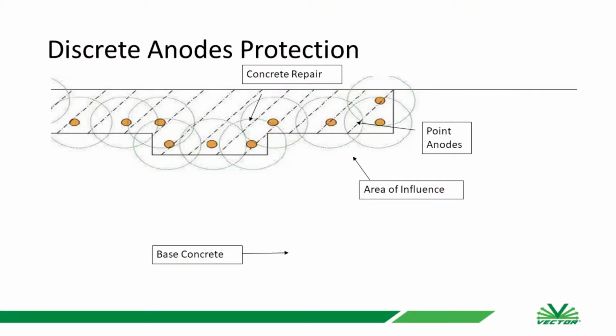Again, you want these anodes around the adjacent of a patch. You want to protect that interface between old and new material. I always like to kind of point out as well, for these galvanic anodes, these aren't going to provide structural protection all over, the ones that I'm speaking about here. You're really going to get that perimeter of the area around your patch where you're going to get most of your protection. If you had another element or another lane down here, it's not going to do anything down there. Zinc can only throw current so far when it's in concrete.